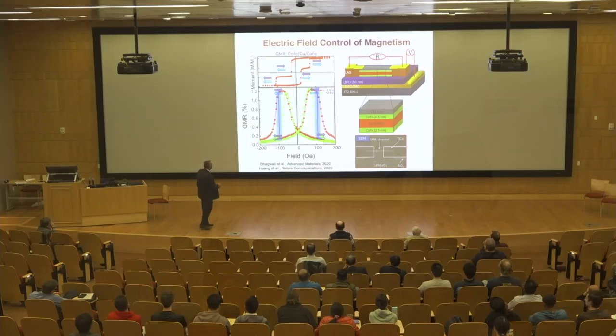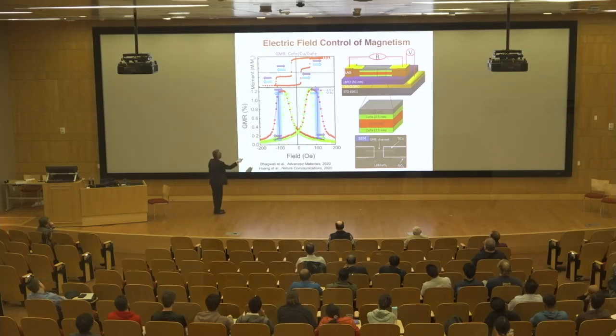This is what Albert got his Nobel Prize for. And you can see that the resistance can be modulated by a magnetic field. Not a big deal. This is not the big discovery. But what is interesting is that the bottom layer, which is this ferromagnet, is coupling differently than the top layer. So you get something that looks like a split hysteresis loop, and more, we can manipulate it with an electric field. You can see the green and the red are different by applying different polarities of electric field. So in principle, what you're doing is manipulating the magnetic state of this layer, magnetized this way versus this way, by applying an electric field.